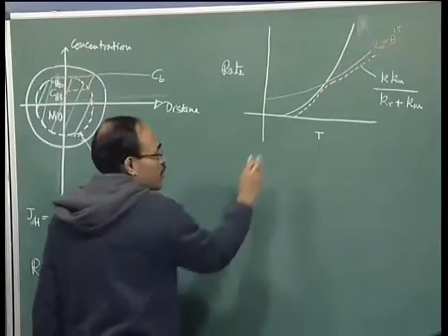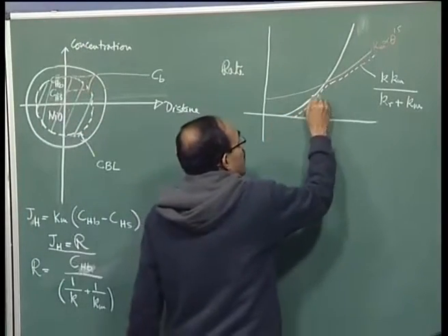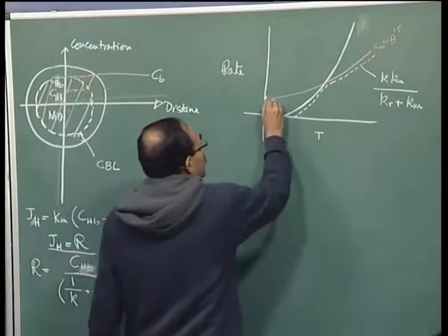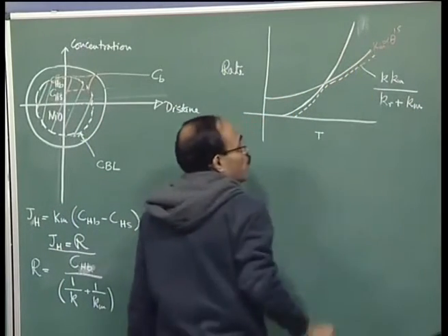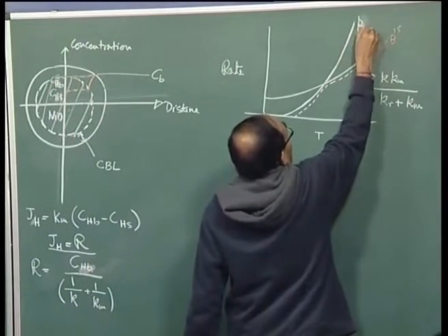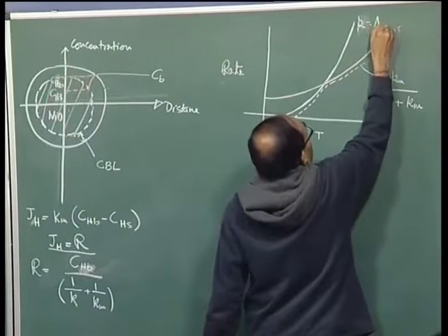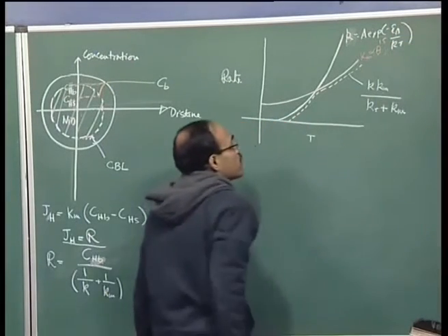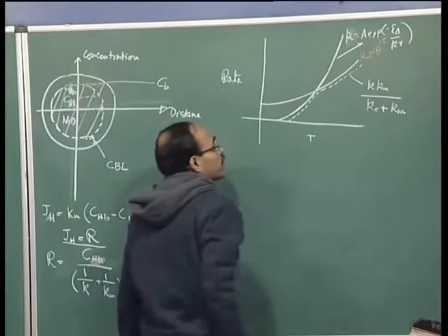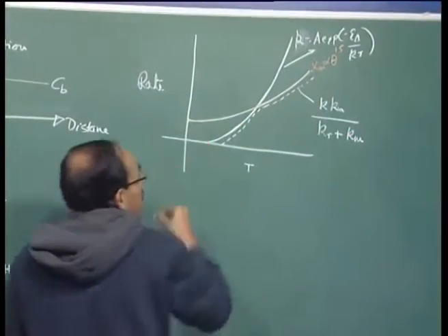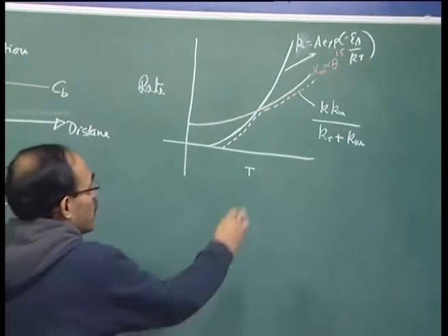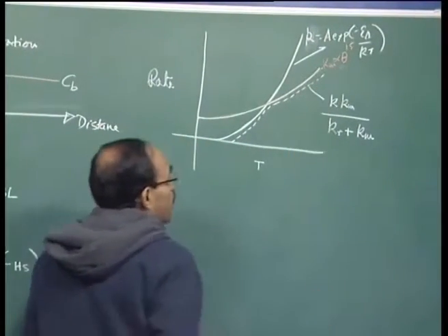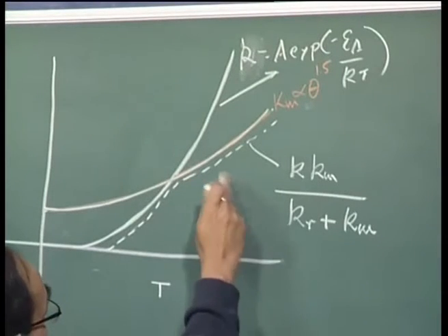you can also plot how the rate varies as a function of temperature. So, this is the steepest line which I have drawn. This line essentially tells us about the exponential rate of variation. This is how the mass transport coefficient varies. So, this is rate constant k equal to A exponential minus E_a by RT. That is what this particular line is, and this tells us about the dependence of the mass transport coefficient on temperature, where theta is the absolute temperature in this particular case, and this gives us a situation when we have mixed control